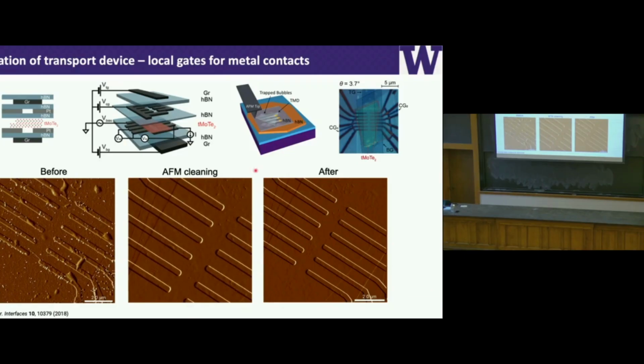So first of all, we have to make a good metal contact. So for each contact, we pattern a local gate on top of them. Okay, so basically for each contact, we have this individual gate, right? To dope the contact areas. So we can dope the sample and then make a good contact.